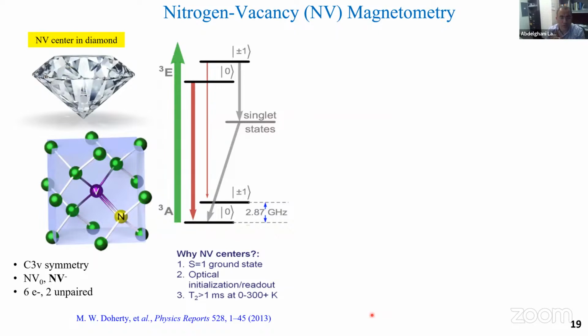For those who are not familiar with this technique, the NV, or nitrogen vacancy, is a defect in diamond. Usually it has 6 electrons, 2 unpaired, in the ground state or excited state, so that you can get a spin triplet, for example, in the ground state. You can optically initialize with light, and then it emits light, and by looking at the emitted light, you can read out the spin states.